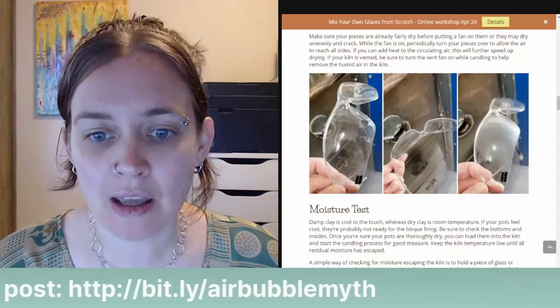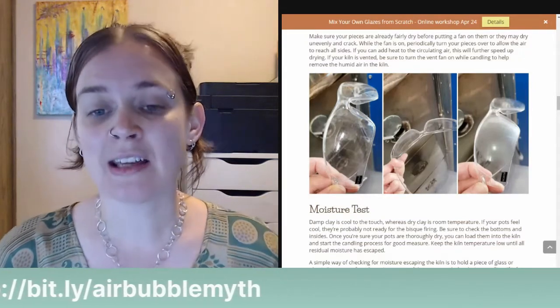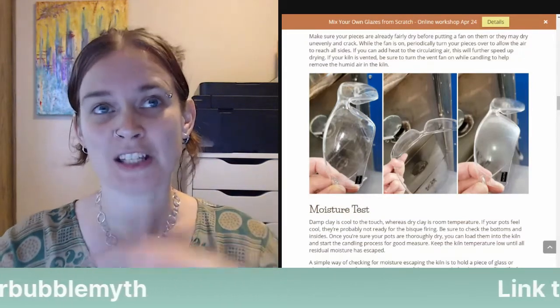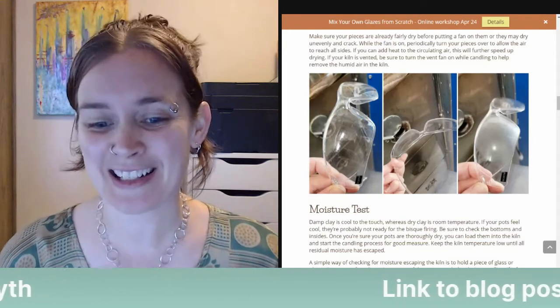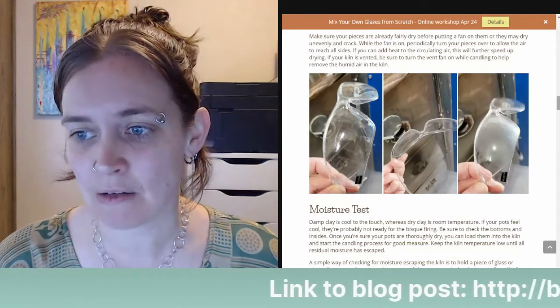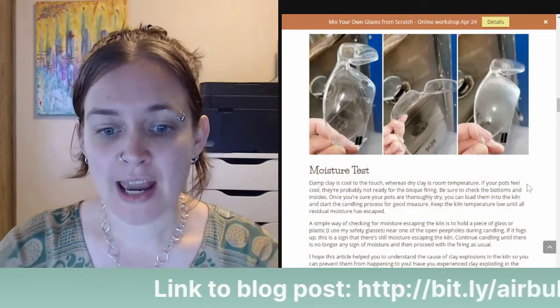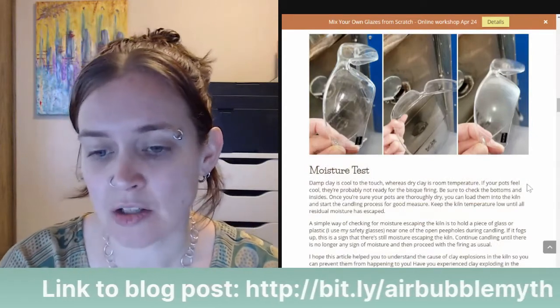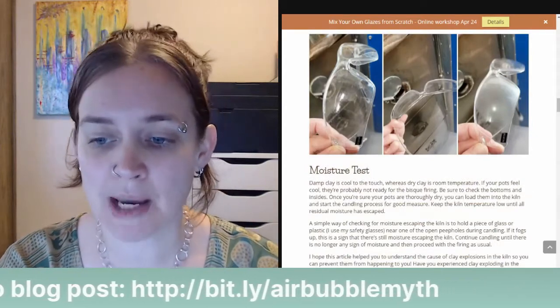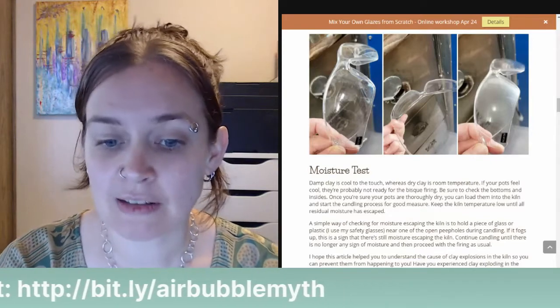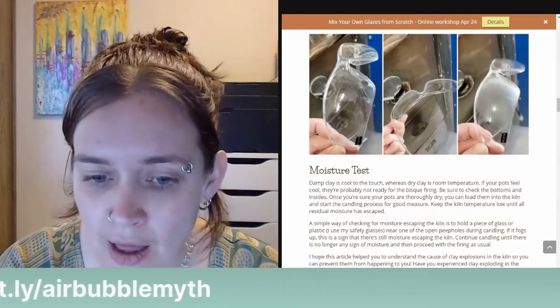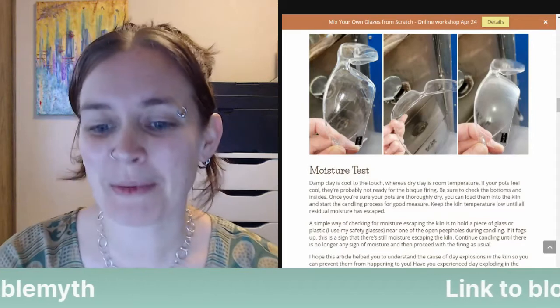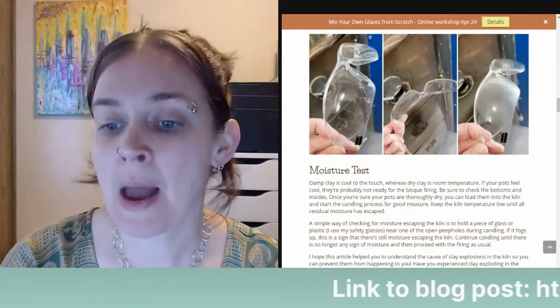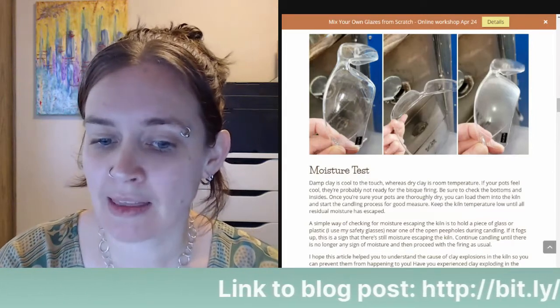But if you want to test to see if all the moisture is finished escaping, then here is a moisture test that you can do. Damp clay is cool to the touch, whereas dry clay is room temperature. If your pots feel cool, they're probably not ready for the bisque firing. Be sure to check the bottoms and the insides.